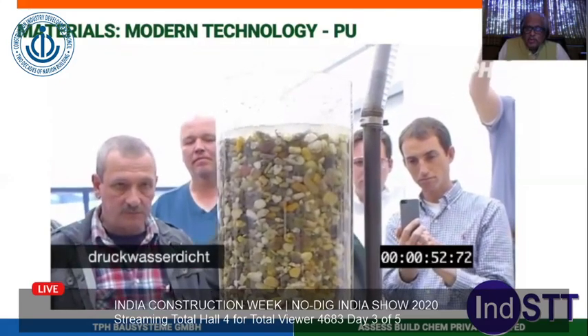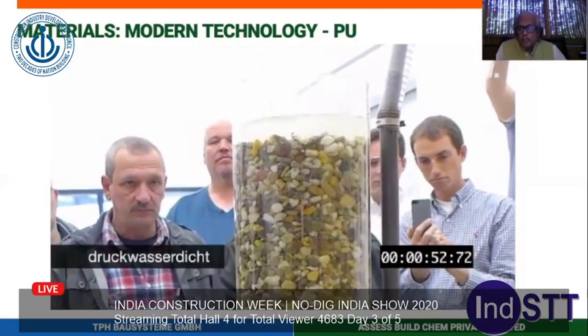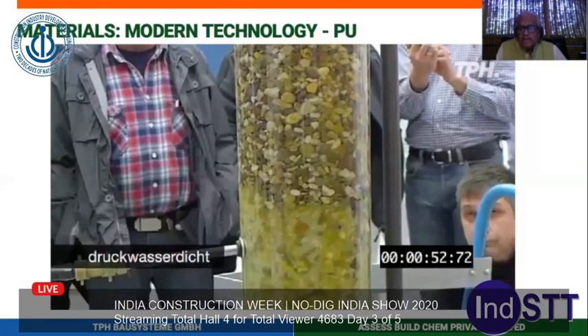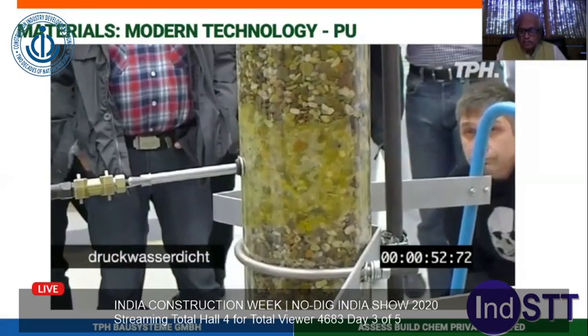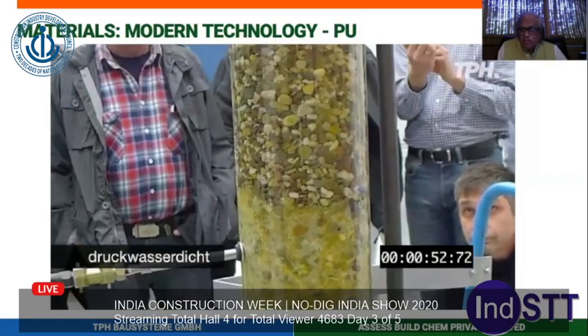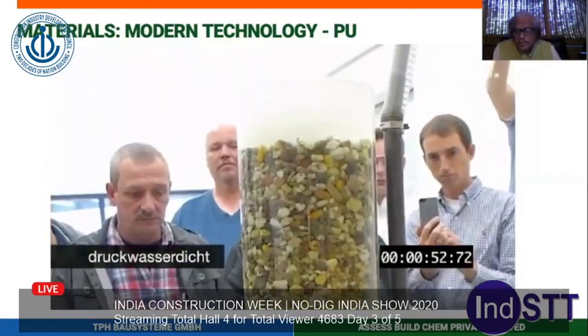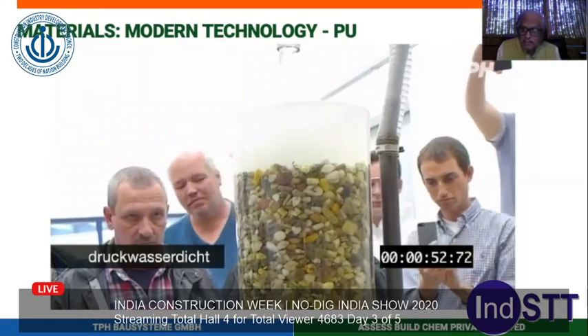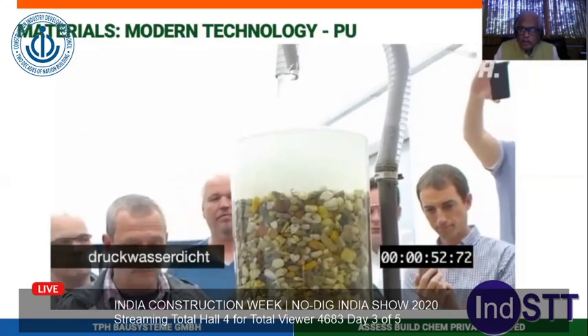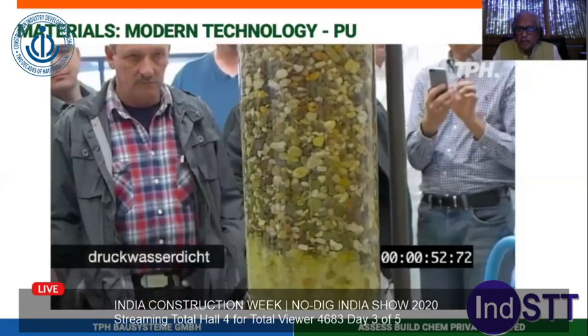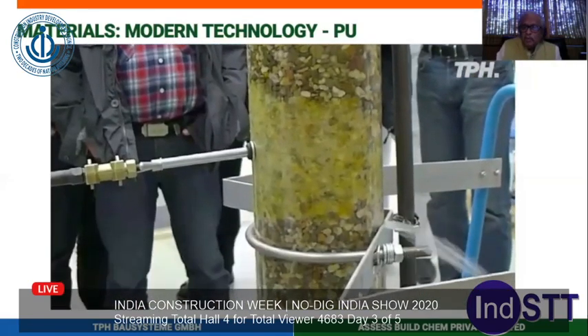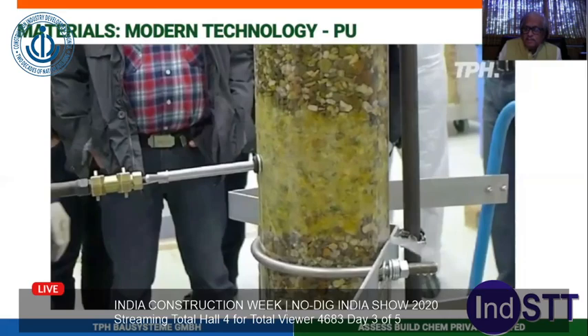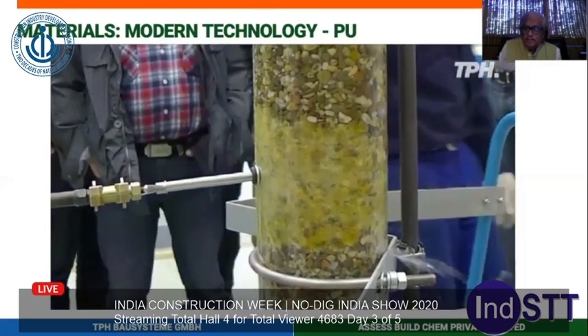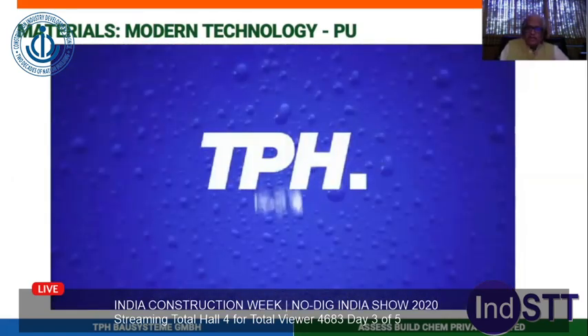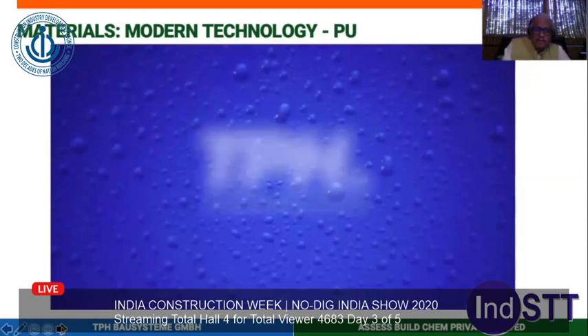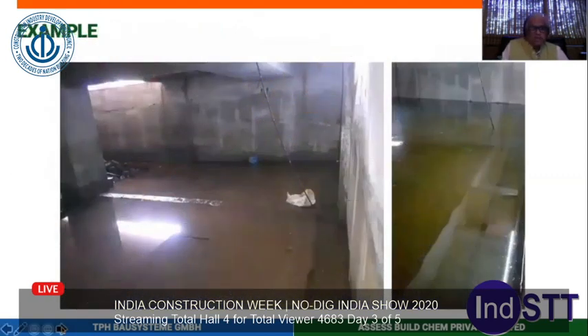If you see now, the water has stopped going inside and the water is rising. If you see from the bottom, the stream of water is getting reduced. It has expanded, not very much, but to a reasonable extent so that it is spread all around. The water from the top is flowing out. The water which was coming out in gushes is now slowly stopping. And within a matter of 1 minute, the total process is over.